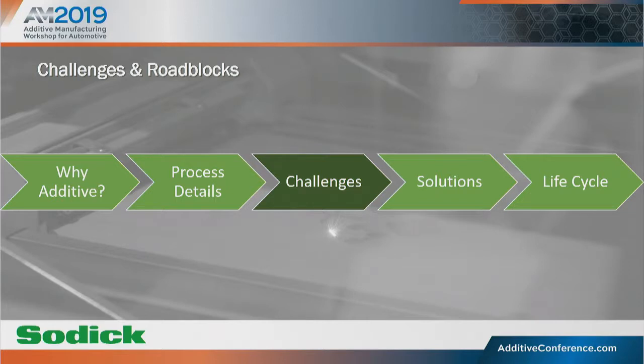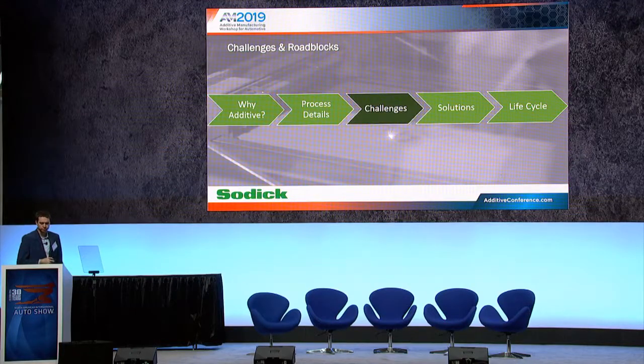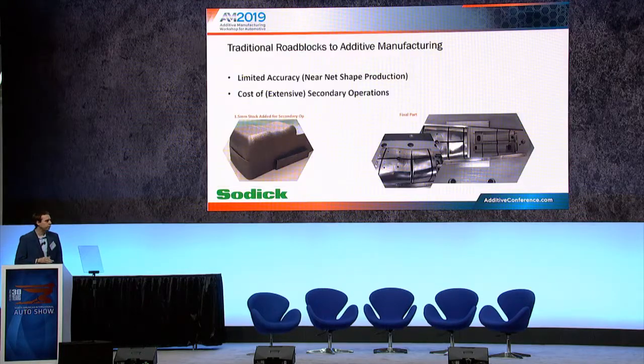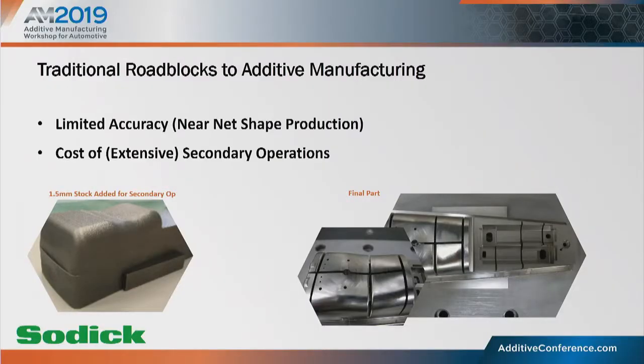So the process is mostly straightforward. So why has it been such a challenge for the most part to implement some of these really revolutionary technologies and experience the gains that you could achieve? Well, probably the number one limiting factor has been the limited accuracy of 3D printers up to this point. In general, 3D printing has been considered a near net shape process, so you're not ever able to really achieve a finished part historically. Because of the internal stresses and the lack of accuracy from the lasers, normally what you'll have to do is leave machining stock on that part. Heat treatments for these parts, which normally have to be done, will cause movement in the steel.